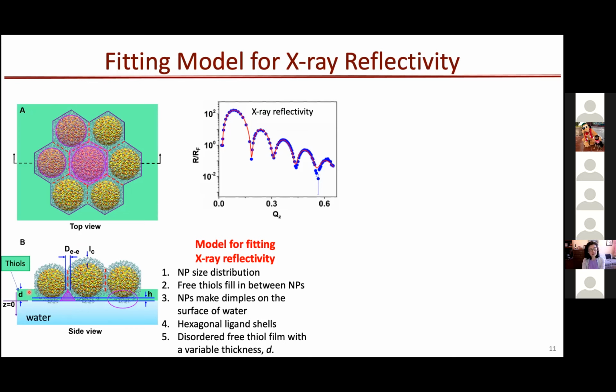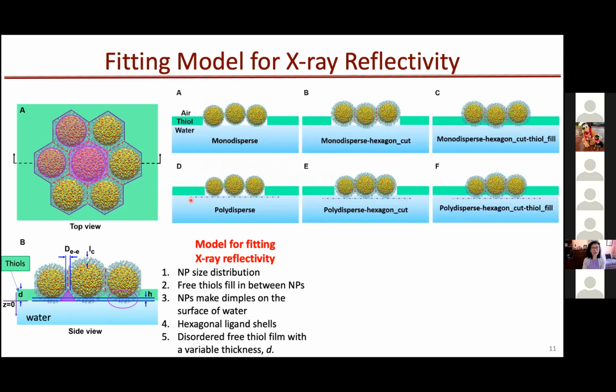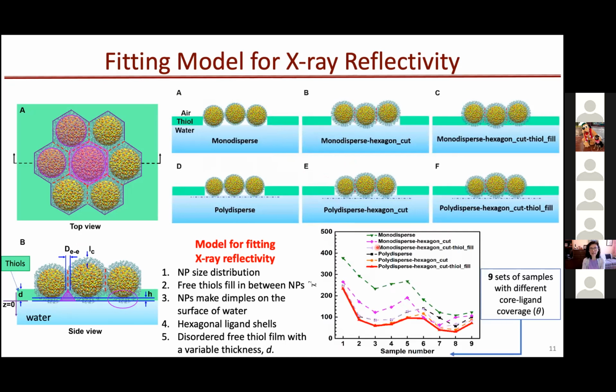Of course this is not the only model I've tried, or PON have tried. There are 5 other models we have tried, from A to E, and as we can see, the model I described gives the best chi-square value. Actually, in the end, what stopped us from further modeling is the fact that the electron density contrast between the gold and the thiol is so huge and large that the data is just not sensitive to more sophisticated models anymore.